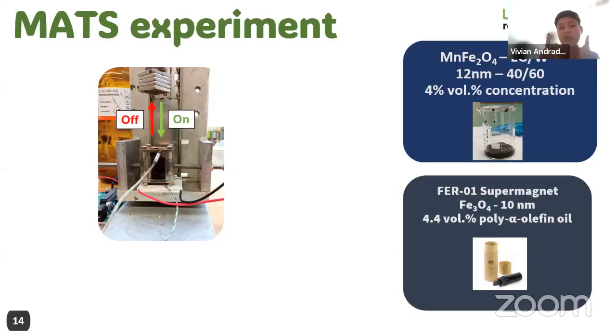When we look at the experiment, we can see that with the paraffin oil, because it has higher viscosity, when the magnetic field approaches, it goes all the way up to the other side. In the case of ethylene glycol and water, it goes more slowly to the top, and then it makes more time of contact. So this is because of the fluid itself.